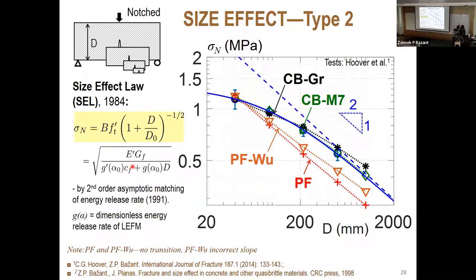And now, this formula has been derived by asymptotic matching. You do an asymptotic expansion in the near linear elastic fracture mechanics, you can get easily the first two terms of that expansion. You do the same on the ductile side, you get an asymptotic expansion, also two terms, so four asymptotic terms to match, and they are matched by only this formula, none other.